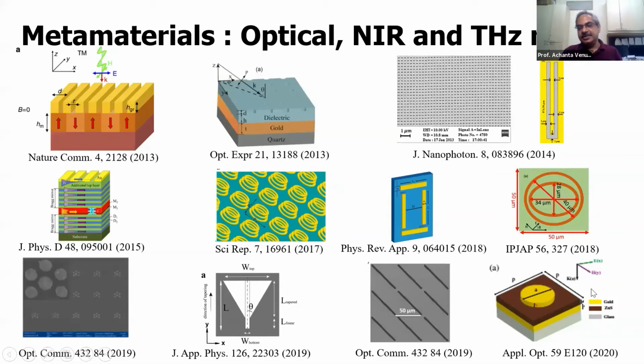this one, for example, the bottom right corner, is a perfect absorber in which, in a very thin, 10 to 20 nanometer thickness, we can have near 100% absorption. And this has vanadium dioxide, which shows a metallic to insulating phase transition close to room temperature. So we can switch these pixels on and off, so it has stealth applications.